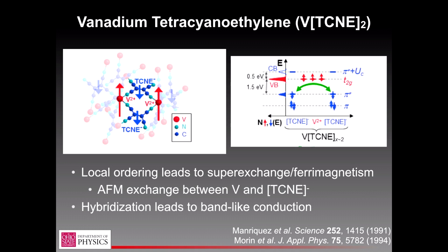You can just do it by counting. You have 3 electrons on the vanadium pointing one direction. The 2 electrons that get kicked off into the pi star orbitals of the TCNE point in the opposite direction. So you're left with 1 net Bohr magneton per formula unit of magnetization.